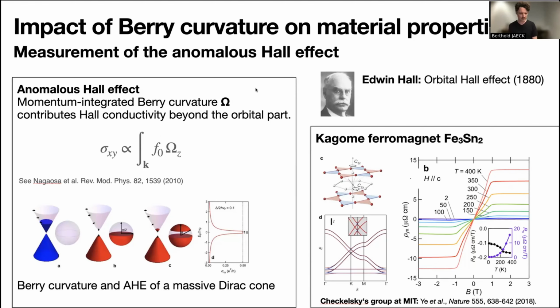I guess a very specific example that we can detect, for example, in Kagome materials is that if we combine a Dirac cone with spin orbit coupling and ferromagnetism, we can essentially get a gapped Dirac cone giving rise to a very strong Berry curvature. In the fully quantized limit, when the Fermi level resides in this charge gap in between, then we can even find a fully quantized Hall response, a quantum anomalous Hall effect.